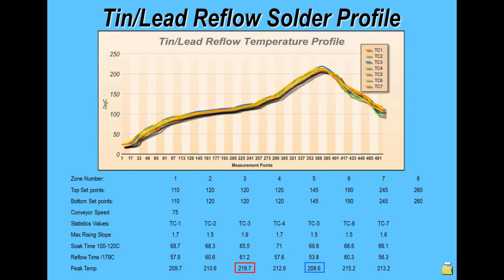Now if we look at the profile here, the actual peak temperatures on this particular example are 220 to 208, and this is for a tin lead reflow process. So the peak temperature for a lead-free process may be 230, perhaps up to 240 degrees Celsius, but that's dependent on the product going through the process or the speed of the reflow soldering process and possibly also the length of the reflow process. If you've got a very small short oven, generally speaking, all the set point temperatures will be higher and the set point for reflow will be higher, and depending on the speed of the board going through the process, the actual product temperature may be higher. Depends on the factors that I've previously mentioned.